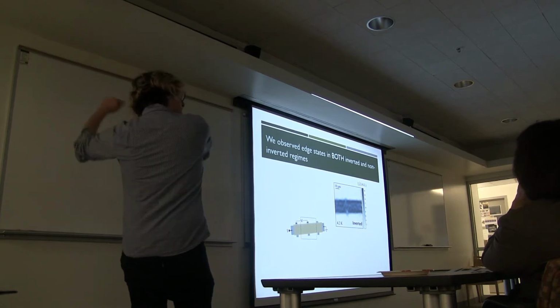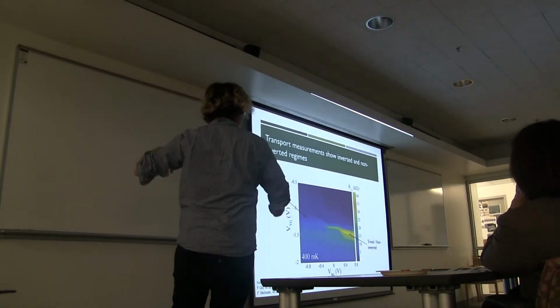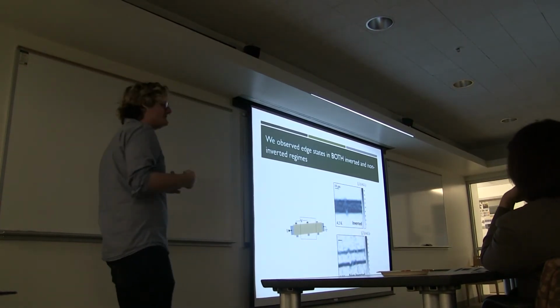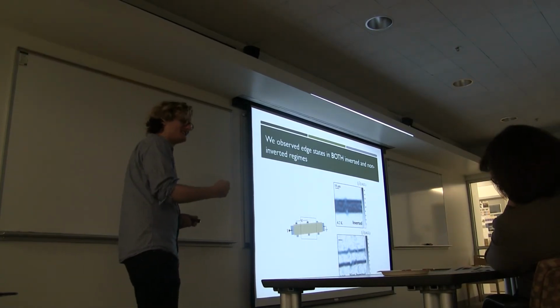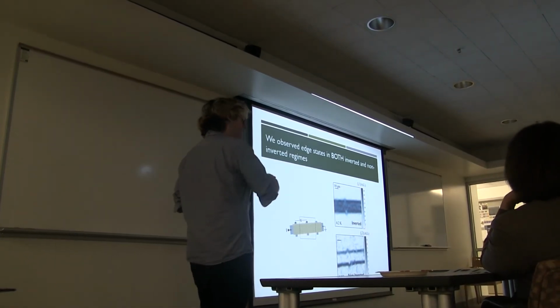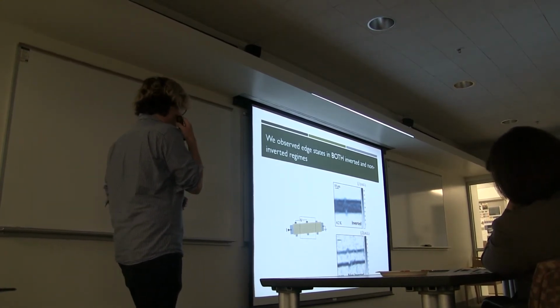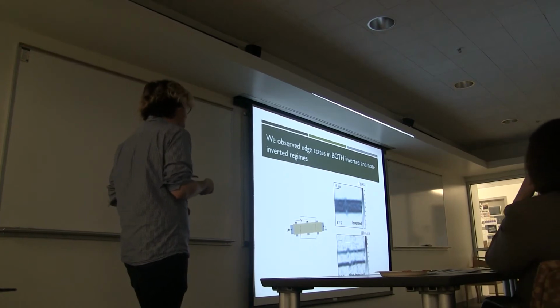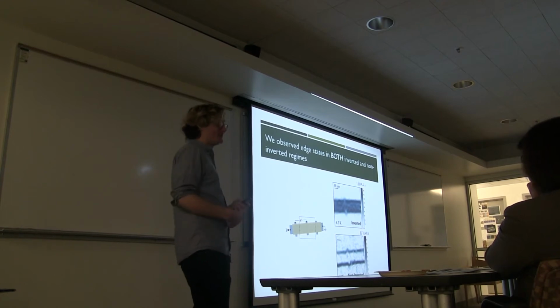So now we take our gate voltage from negative to this weakly resistive region to the inverted regime, and what we find is that the current in the non-inverted regime is completely carried by edge states, which is not what you'd expect for quantum spin Hall edges. So that's quite surprising, and it's been shown in transport that these edge states can actually mimic the quantization effects that you expect to see.